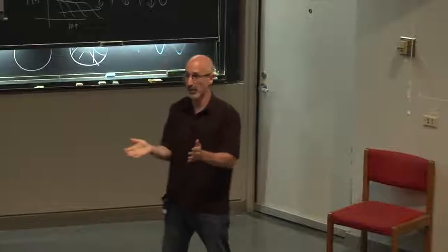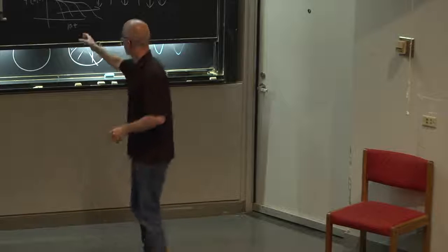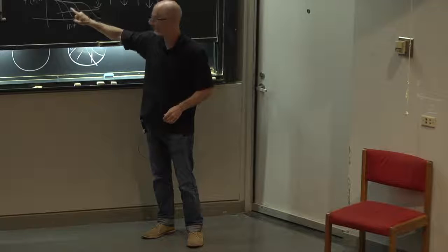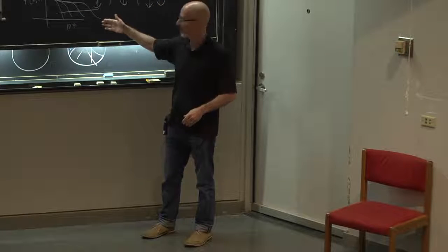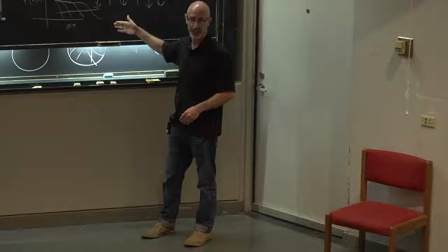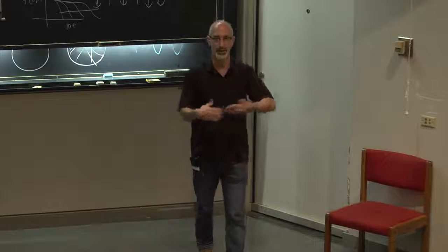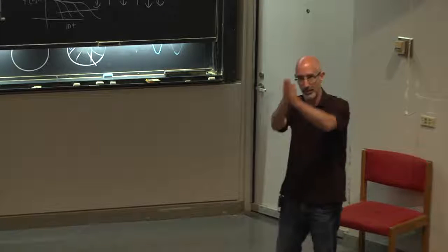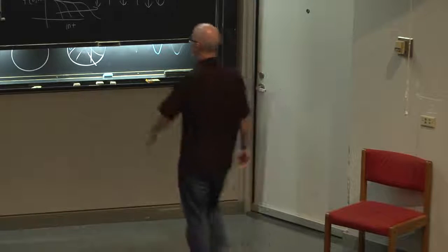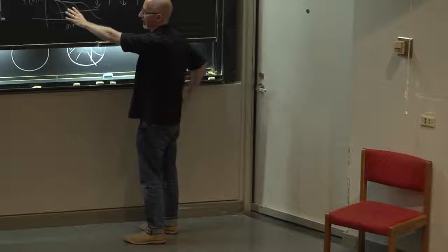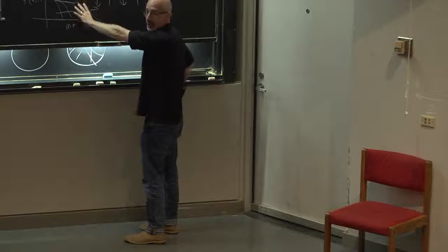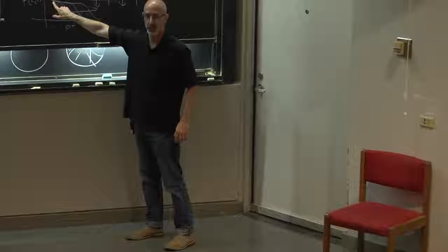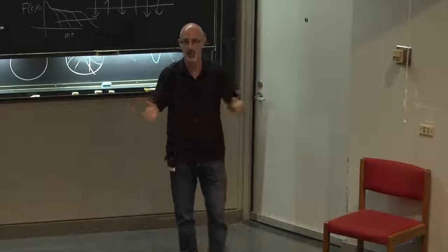Okay, so what you can do is open up a window, which is not surprising, where the infinite dimension system lives for a longer time scale. If you go to an even longer time scale, let's say in 5 dimensions, you eventually get to a relaxation time where you see hopping and you see violation of Stokes-Einstein. But if I go to a higher dimension, I have to go to a longer time scale to see that. You open a bigger and bigger window where the mean field type dynamics that you expect in infinite dimensions lives. Okay? But the chi-4 is growing always at the onset of supercooling. So you can separate these two things more and more and more.